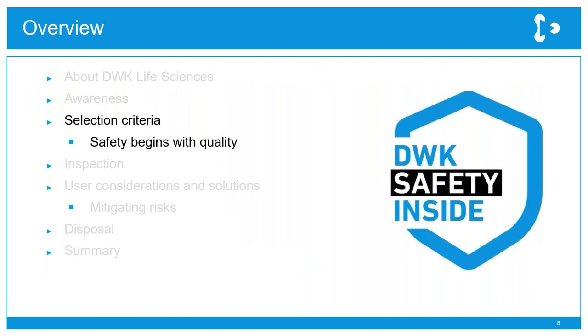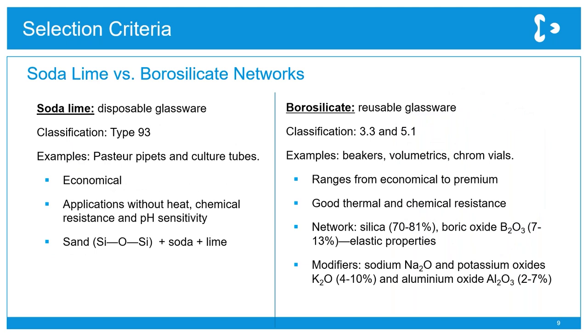So safety really begins with quality and also selection criteria. So there are two types of glass that are commonly used in the lab, and that's soda lime and borosilicate. Soda lime is usually used for disposable glassware, so things like Pasteur pipettes and culture tubes. And this application tends to not involve heat, and it would be something where chemical resistance and maybe pH sensitivity aren't important. And the formulation is very simple. It's sand plus soda plus lime.